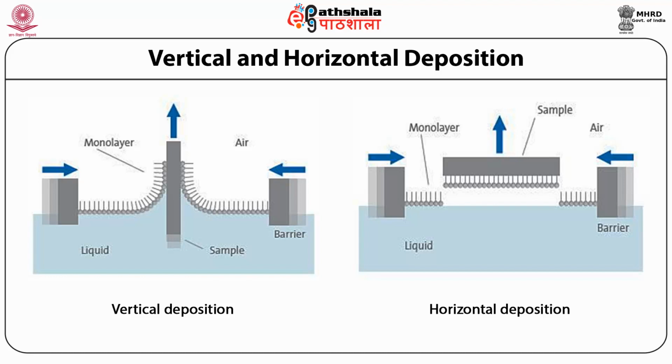On the right hand side you can see that we can also use the deposition technique in a horizontal way. Here we have a hydrophobic surface, and we just bring it close to the layer and touch the water surface from above, and this hydrophobic tail will stick to this hydrophobic surface, and in this way we get a deposition of a monolayer in a different way.